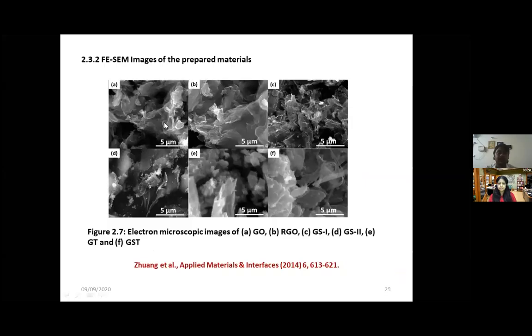And these are the microscopic images of the prepared material. This is graphene oxide and reduced graphene oxide. Graphene oxide is usually a wrinkled 2D structure, a single sheet of carbon. For high resolution images we will go to the next images, but these are the scanning electron microscopic images of GO and reduced graphene oxide, and of GS1, GS2, GT and GST, all the four sensor materials. Even though the structural characteristic is not evident here, we can appreciate the structural synergism between the graphene oxide and the metal oxide here.